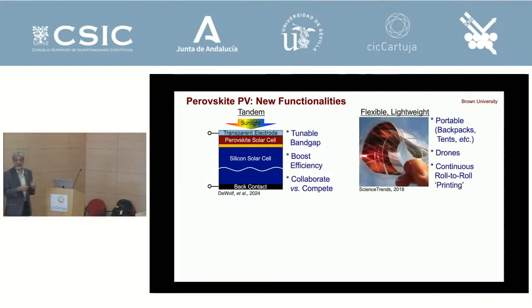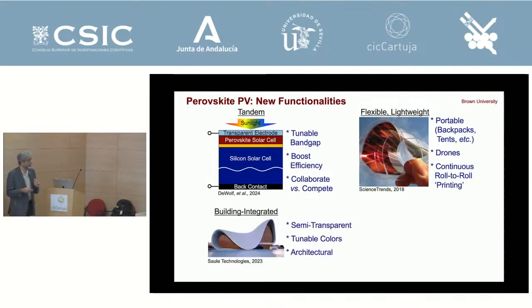And then since these are thin film materials, 500 nanometers deposited at near room temperature, you can put it on plastic, lightweight, for drones, tents, deployable solar cells. Then you can actually tune the band gap and you can make it building integrated. So you have a wall which is basically collecting sunlight, producing electricity, and it's all looking beautiful. So you can do that. You cannot do it with silicon. Silicon is ugly black, right?